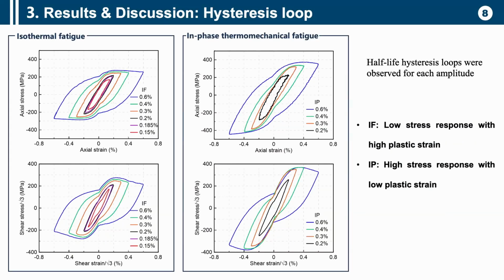Then I show the hysteresis loops. This is the half-life hysteresis loop. For each amplitude, we put the tracks together. The left figure is isothermal fatigue, IF, showing the axial stress and the shear stress. You can also see that for IP, the loading has a higher stress response. For shear stress, we can see the maximum stress arrive and then the stress relax because of the 90-degree out-of-phase loading.